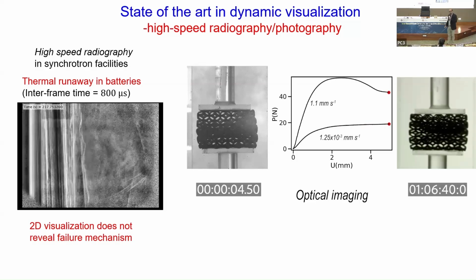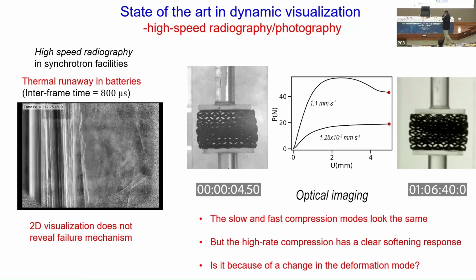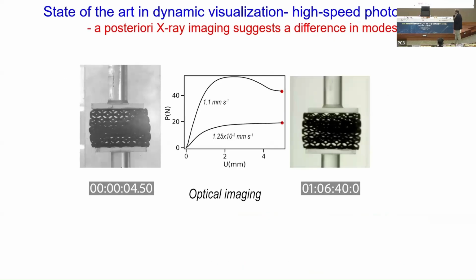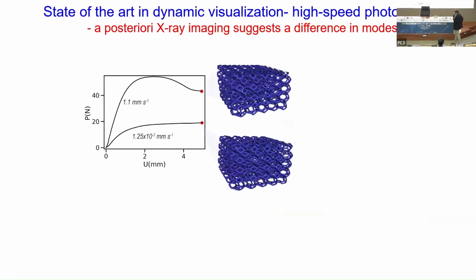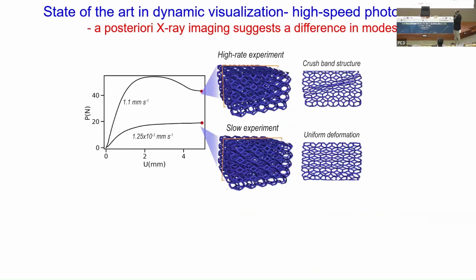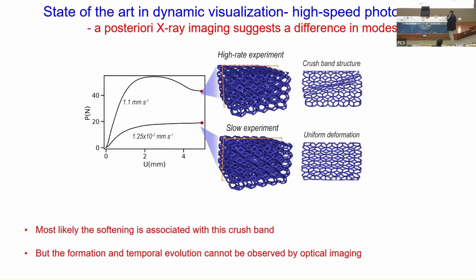But if you were closely observing the optical imaging, what you observed is that the deformation mode looked the same in both cases. The slow mode and the fast mode look the same. But there must be something different, because there was softening occurring in the high rate deformation, and the slow rate deformation was not giving you the softening. But the 2D imaging, which is essentially optical imaging, did not tell us what the difference is. Well, if you look at the specimens in an X-ray image after the whole thing was finished, you'll see there was a crush band that formed in the high rate experiment. And that softening must have been due to that crush band.